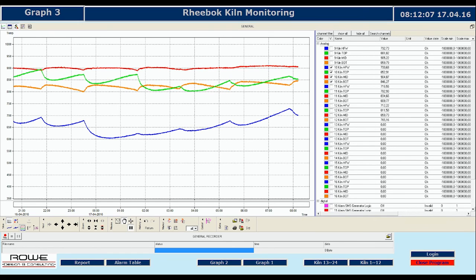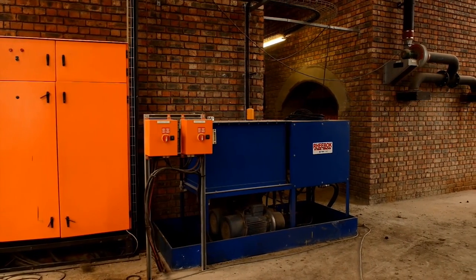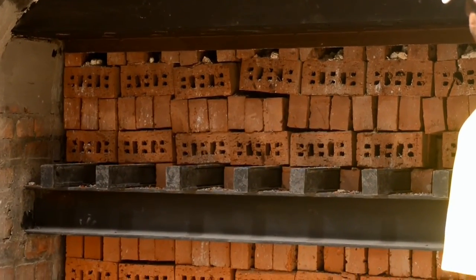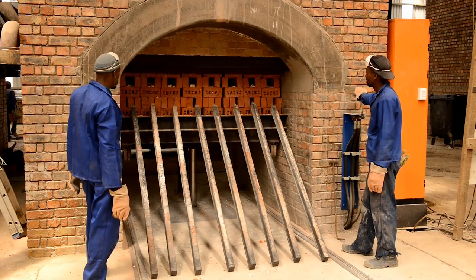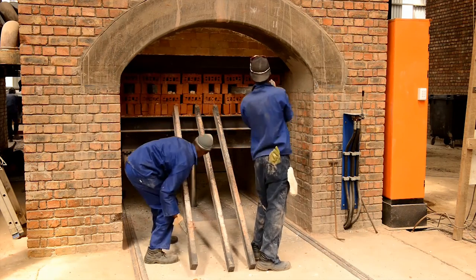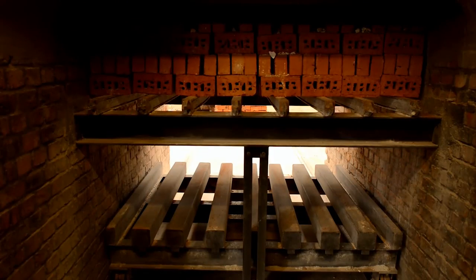The system provides full 24-hour operation coverage and fallback capability. A centrally positioned hydraulic system provides a means to lift brick batches to enable a single batch unload of each kiln. Unloading is achieved by raising the trolley to the underside of the brick batch. The batches are then raised to release the support bars, which are removed by hand. Bricks are lowered until the next support bar layer is apparent and bars are reinserted. Bricks are then lowered to the floor with support bars holding the fired bricks above. When the bricks have cooled under the shaft, they are removed for unpacking and transportation to the dispatch area.